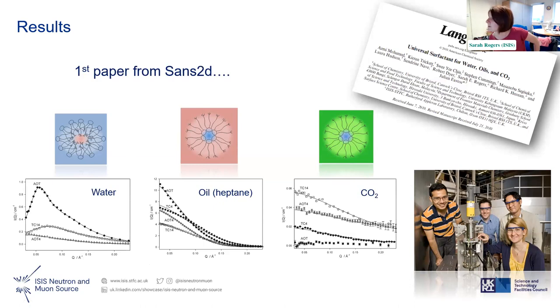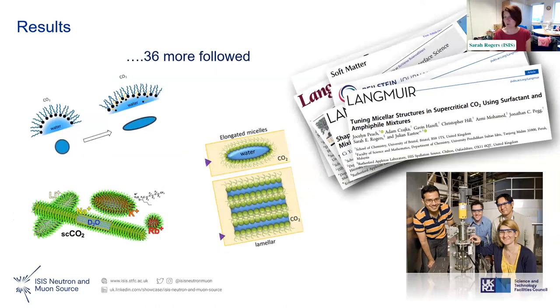That pressure cell is actually, as you can imagine, solid steel, but the windows are sapphire. They're C-axis cut sapphire, and they're very chunky because they can go up to a couple of kilobar, but they're actually totally transparent to neutrons because we pick sapphire. So again, it shows you can design these really complex pieces of sampling environments. But if you think about the neutron properties, as long as you design the windows out of the right material, the sampling environment becomes transparent and you're only scattering from the sample that you're interested in. It's really powerful. And then 36 more papers have followed.